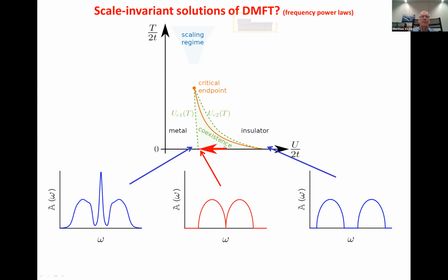One phase is metallic, and this has a quasi-particle peak in the middle. The other phase is insulating, and this has no quasi-particle peak in the middle, and really has zero or very small spectral weight at the Fermi level. Again, in actual experiments, you can very nicely see this in these organic Mott insulators, which can be tuned by pressure. There is this coexistence regime, and you can see domains which you can even image by STM techniques, and you see insulating and metallic domains.